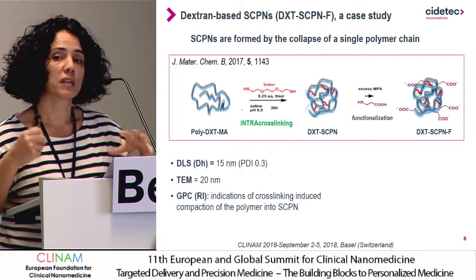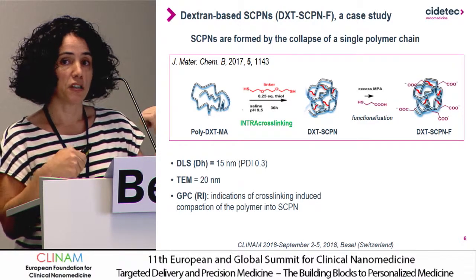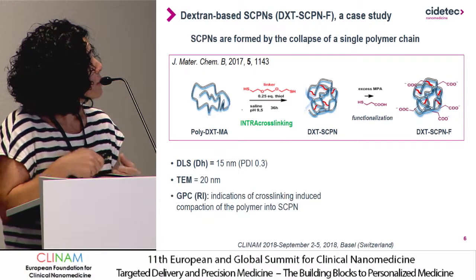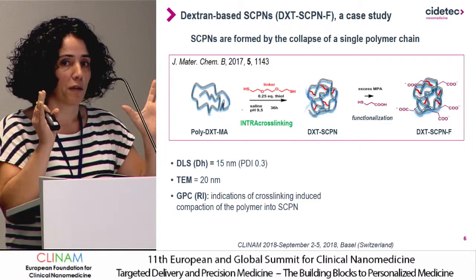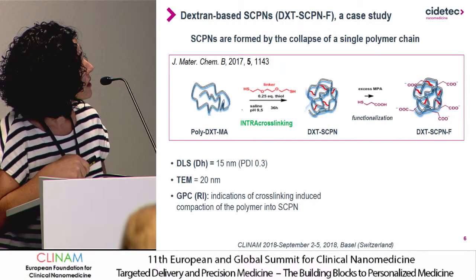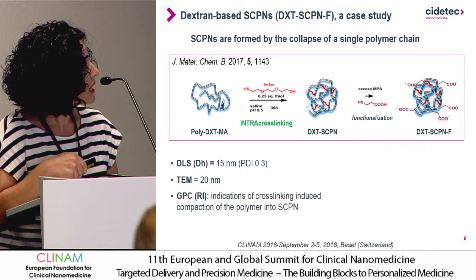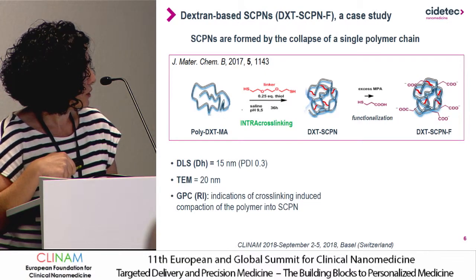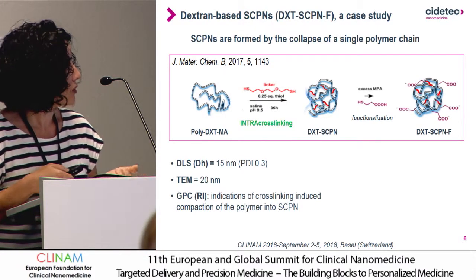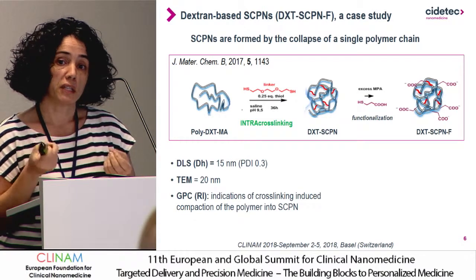I will show you now some of the work that our group is doing in order to prepare this technology, this development, to go into a GMP production process. It is just part of the work we are doing, because the work you need to do is huge. Single-chain polymeric nanoparticles are formed by the collapse of one single polymer chain by the addition of a homobifunctional cross-linker into a polymer solution. After, it is functionalized to obtain the final nanoparticle. The size of our product, around 20 nanometers, is one of the critical quality attributes,